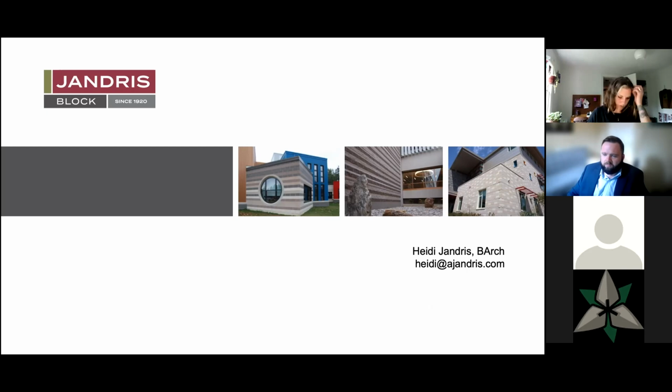Yeah. So I have preliminary testing just on that block that I showed. NCMA is currently working on several different producers and their blocks. So I can only speak to what our block showed. And it showed a range of 25 to 28% at fully carbonated. So it is somewhere in the ballpark of what you just mentioned. And I'm sure it's going to depend. I'm sure there's going to be regional differences, right? Some different producers have different aggregates that are going to change these numbers. That's one of the things the NCMA is trying to pin down: are there regional differences, what are they, and just start trying to get a baseline of that.